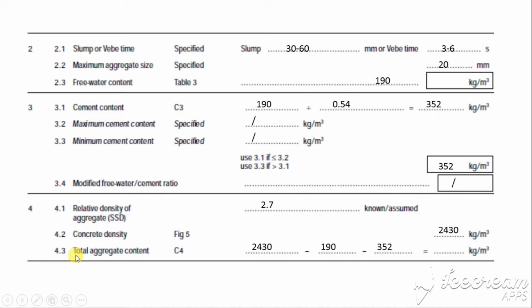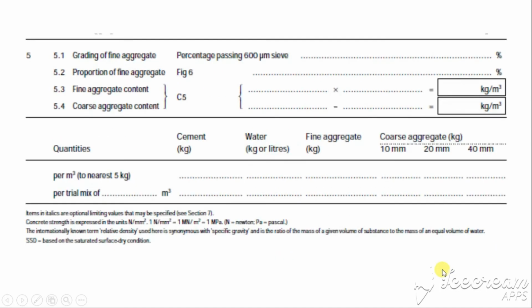And then to calculate the total aggregate content, use the formula from C4. 2430 minus 190 minus 352, you will get the total aggregate content 1888 kgs per meter cube. Okay, we go to the next stage, and this is the last stage.